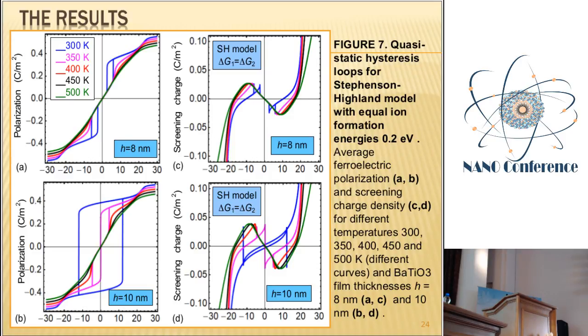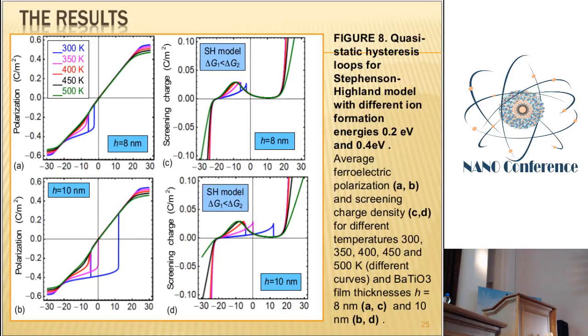For different formation energies, we have a so-called strongly distorted loop. This loop is neither single nor double. It is a so-called minor loop. For one direction of external bias, you have a loop, and for another, you have a linear curve. And with the thickness decrease, this loop looks somewhat similar to the single loop, but is very truncated and irregular. This is because our formation energy is different, and for one direction of the applied voltage, ions help to conserve the polarization, but for the other direction, they only help to destroy it.